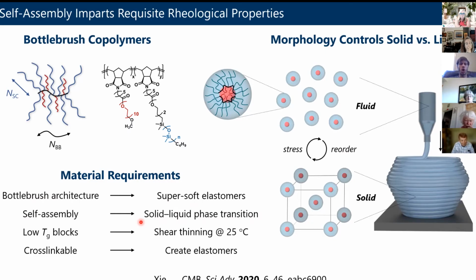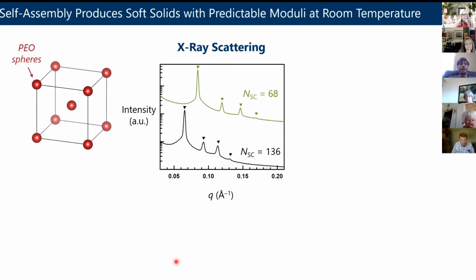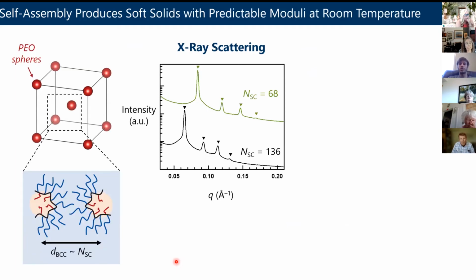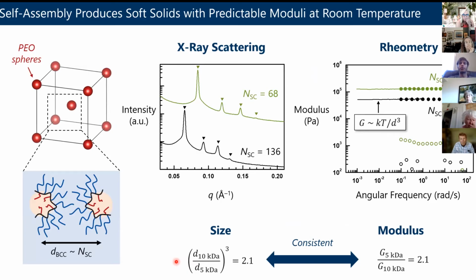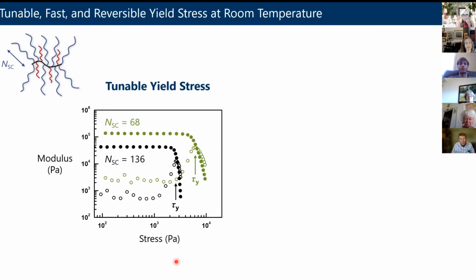We use low Tg blocks, like we've been talking about all through the presentation, to allow this process to happen at room temperature. Everything wants to be a liquid. It wants to flow at room temperature. And we dope in a little bit of benzophenone, which isn't pictured on the slide, but it's the same chemistry we saw previously because it's cross-linkable, and that will actually create the elastomers once we're done. Now, I'm going to skip this characterization in the interest of time, but we characterize these materials in a variety of ways, including X-ray scattering and rheology like we've seen previously.